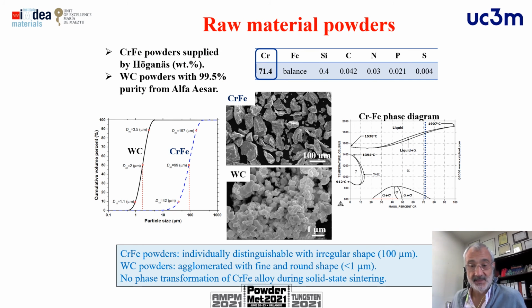The starting powders that we have used are two different families of powders, of cemented carbides of a small size. Here you have the particle size distribution of this tungsten carbide, and also we have used chromium iron powders, with a percentage of 75 of chromium, 25 of iron as balance, and this powder was supplied by Höganäs in Sweden. The chromium iron powders are more irregular than the tungsten carbide, which is more spherical, and due to the small size of these particles, they tend to be agglomerated.